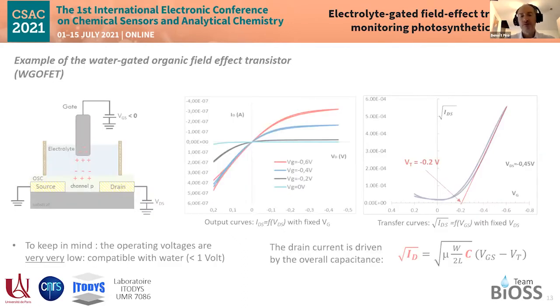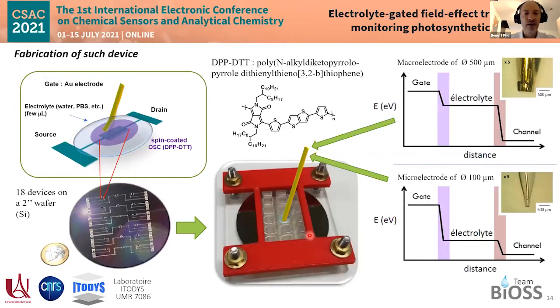That way, first I could say that these kinds of devices are relatively easy to fabricate by conventional microfabrication strategies on silicon wafer, for example. Semiconductors are available even commercially, and we can adjust the size of the components of these transistors and typically adjust the area between the gate and the semiconductor area, and it makes devices relatively different in the sense that if the gate is, say, large compared to the area of the semiconductor, then the polarization, the voltage drop at the gate is going to be minimal, and the voltage drop at the electrolyte semiconductor will be maximum. On the contrary, if the gate is small, then most of the potential drop is between the gate and the electrolyte.